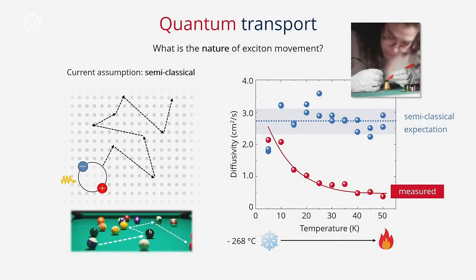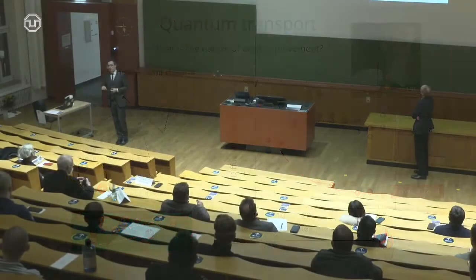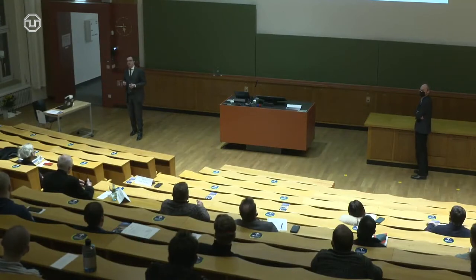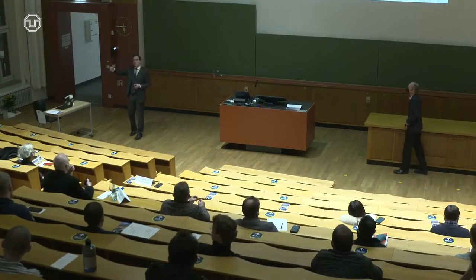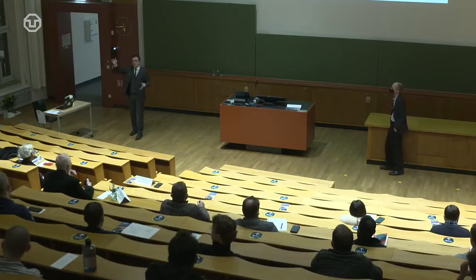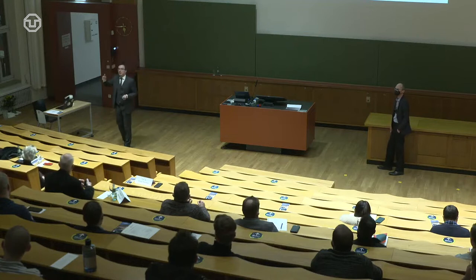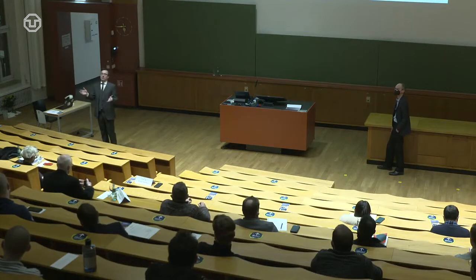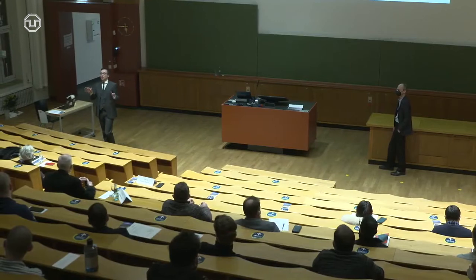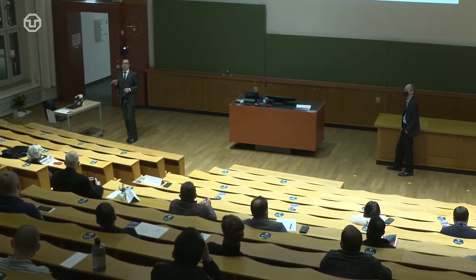Let me just go back here because I think this is a relevant slide for this. So around 5 Kelvin, we're talking about a couple of picoseconds in a clean sample. And over the first, let's say, 50 Kelvin, it's mainly interaction with linear acoustic phonons, so long wavelength phonons, and it will grow linearly with temperature with something like 50 micro eV per Kelvin. I'm talking in energies, right, but something like 10 meV at 50 Kelvin, so we're talking about 100 femtoseconds, going from a couple of picoseconds to femtoseconds. And at room temperature, of course, you go down to 20, 30 femtoseconds due to phonons.